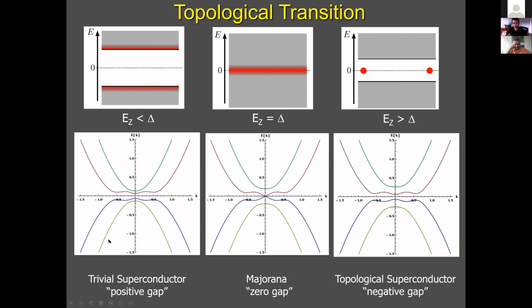Why don't we close gaps at finite momentum? That's because spin orbit field protects us. You can think of it as you already have a ginormous field in the spin orbit direction, and you apply a tiny field transverse to it, which is the external field. And so the total field doesn't change, and therefore this gap is not affected. It's kind of protected by spin orbit. So only the middle gap closes until at a certain point it closes completely. And that's when exactly the Zeeman energy is equal to the gap.